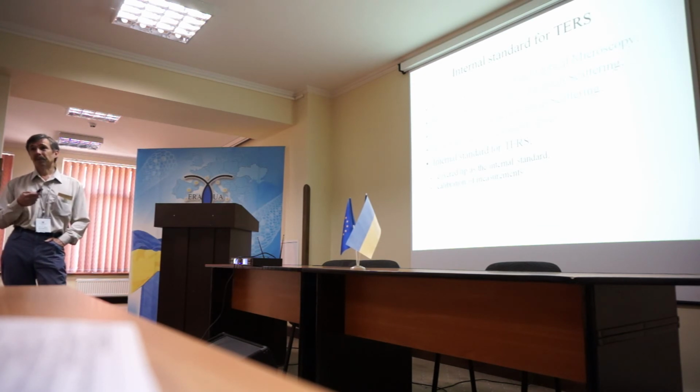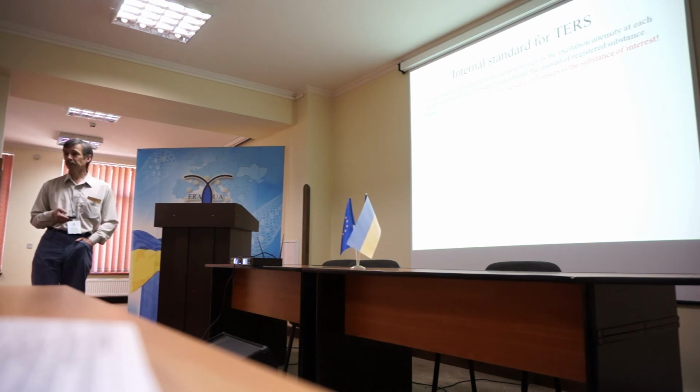And surely, if all of them are only ideas, we can immediately try it as an internal standard for TERS. Because TERS, as a method which uses local enhancement, suffers from an unknown distribution of this local enhancement. In SERS we integrate our signal over the surface and may more or less use the averaged signal and compare different substrates. In TERS we have no idea what the local enhancement is there, and we should either use some other method to measure this local enhancement.